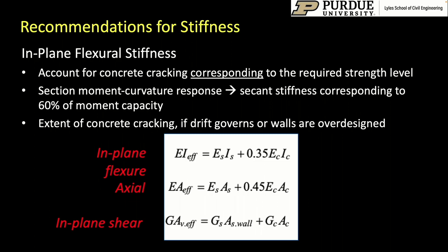What you'll notice is that the concrete has a contribution of only 35%, acknowledging the fact that it's cracked concrete. We're providing a recommendation for the axial stiffness, which again is 0.45. These two numbers actually correlate very well with each other. They're based on the same amount of concrete cracking. And for the in-plane shear stiffness, we recommended just using the full uncracked composite stiffness of the section, because it doesn't really matter for the applications that we are looking at.